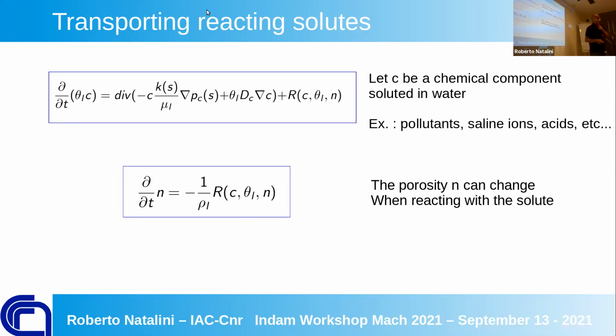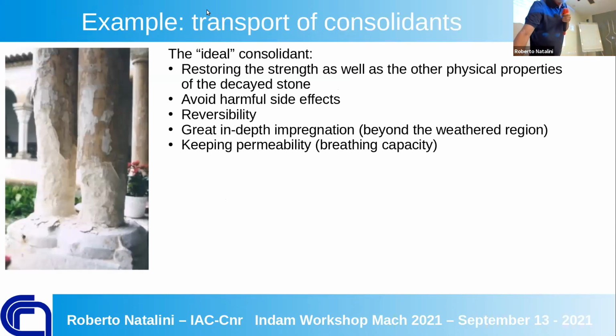This is difficult to deal with, especially from the analytical point of view, because all the theorems of regularity we have to prove again by using other techniques, because usually they are not satisfied by this kind of changing porosity. An example is the transportation of a consolidant, which is usually a sort of chemical component you add with the water or white spirit inside of a material to try to improve the strength of the material. So if you see some powdering of the surface, some damage, you try to consolidate. So you have to make an impregnation of this kind of material inside of the stone.